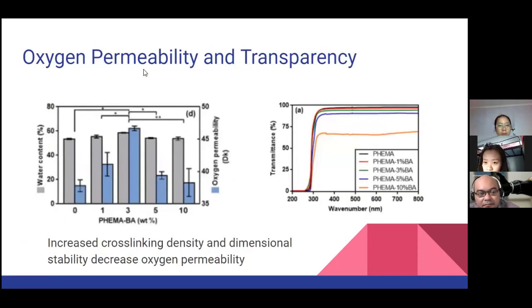Next is the oxygen permeability and the transparency. Yeah, these are both important parameters. As for the oxygen permeability, I have explained earlier. And as for the transparency, our contact lens should be transparent, so we could see. But if the materials are blocking our vision, then the contact lens couldn't be used. And this is the oxygen permeability. This is interesting. Why? Because as we can see, with increased boric acid, the permeability also increased, but then it decreased after 5 and 10%.